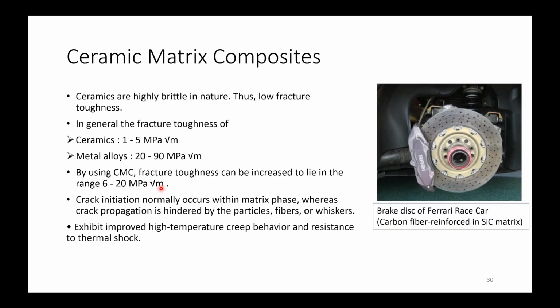square root meter. Now, crack initiation normally occurs within the matrix phase, whereas crack propagation is hindered by the particles, fibers, and whiskers. It exhibits improved high temperature creep behavior and resistance to thermal shock. Now, the brake disc of a Ferrari race car is made using carbon fiber reinforced in a silicon carbide matrix.